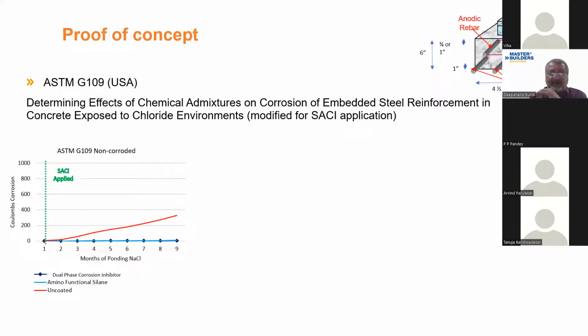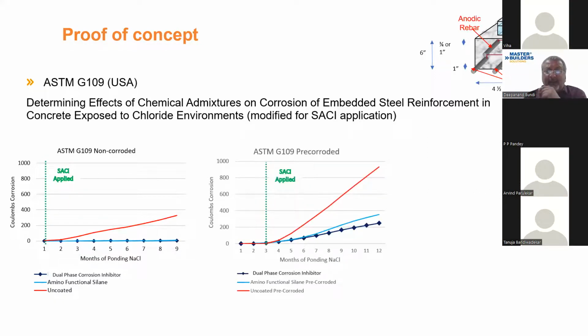In the center graph, the specimens have been ponded for several months to initiate corrosion. So here we have already made the reinforcement bar corrode, and then the surface-applied corrosion inhibitor was applied. You can see that corrosion activity is very high on the uncoated bar. It is marginally lower on the amino functional silane, which is another product from MBS itself. This is the single phase and this is the advanced dual phase. So even after initiation of corrosion, the further growth of corrosion is very curtailed in terms of the amount of charge passing.